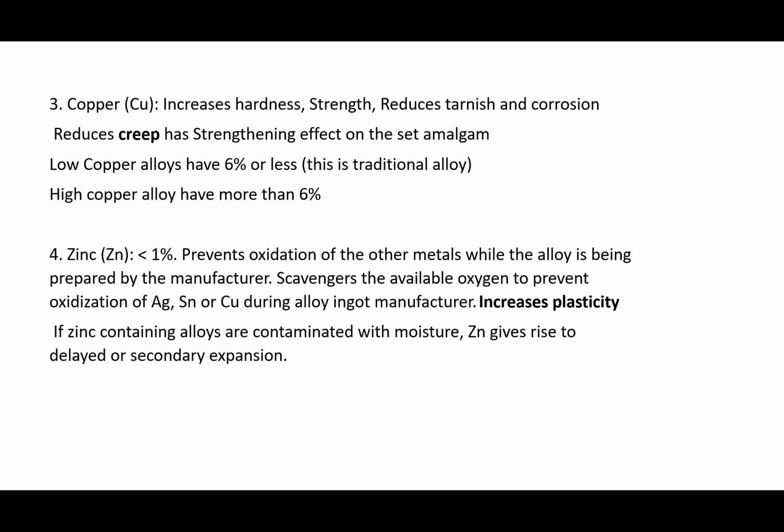Zinc is so important. Zinc is for better handling properties, to reduce brittleness, increase plasticity, and works as a scavenger to prevent oxidation of silver, tin, copper during alloy ingot manufacture, but it has a disadvantage: when the alloy containing zinc is contaminated with moisture, zinc reacts with the water, producing zinc oxide and hydrogen gas, which can lead to delayed or secondary expansion.